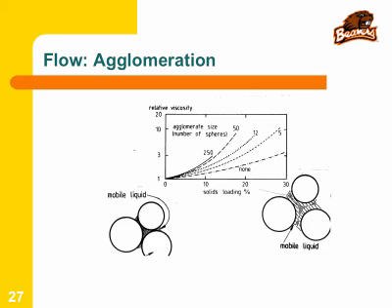And they found that as agglomerate size increased for any given solids loading, your viscosity went up. And then what we said was if the particles are separated from each other, the liquid is free to move. And if the particles, going back to your comment, right? Immobile liquid, if the particles are connected, and if the particles are well dispersed, you have mobile.